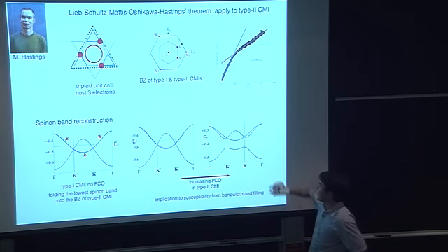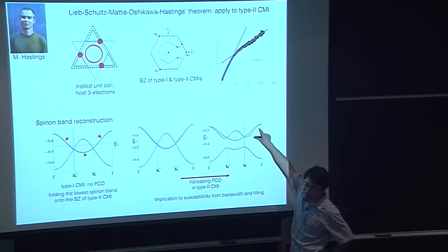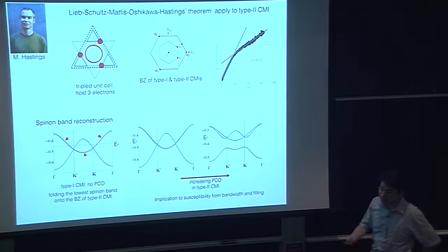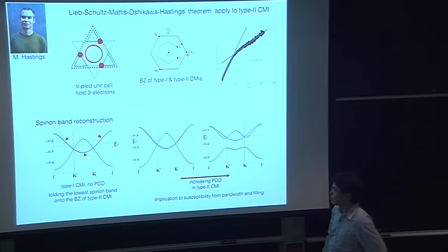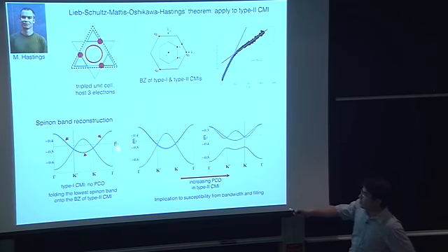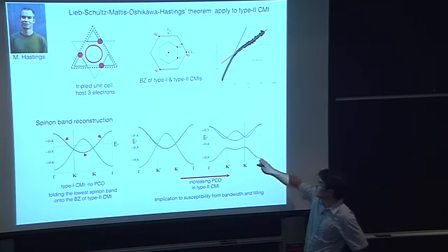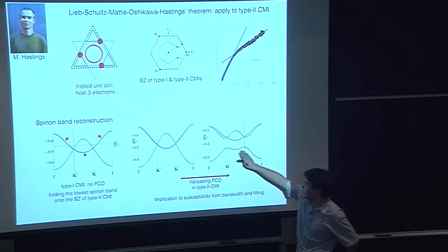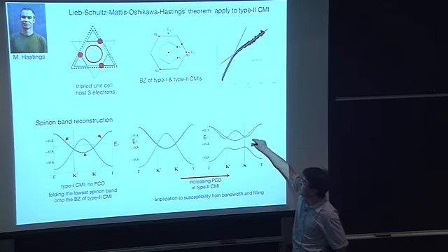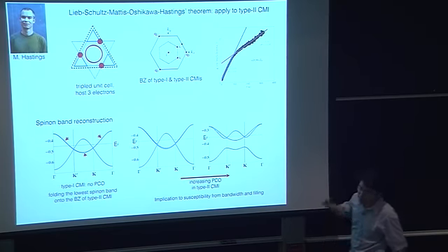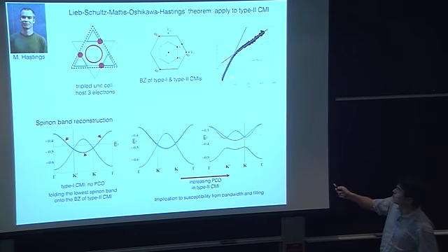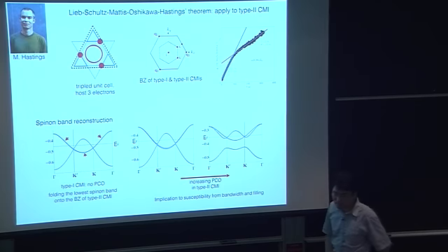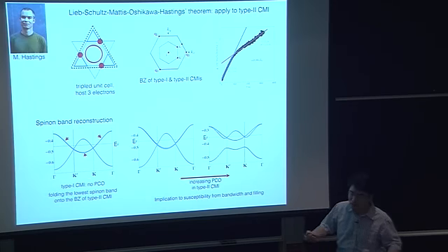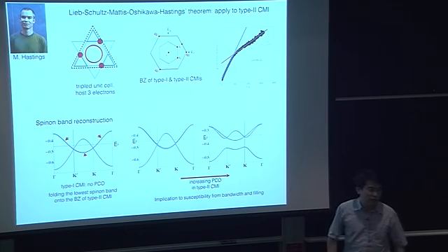On the other hand, the bandwidth of this partially filled band gives you an estimate of the Curie-Weiss temperature at low temperature. Without the plaquette charge order, the bandwidth is large. This would be the effective bandwidth. Now, if we increase the plaquette charge order, this band is completely filled and inactive to the magnetic field. Only these bands are active. The effective bandwidth measures the Curie-Weiss temperature. So this tells us why the Curie-Weiss temperature is very small at low temperature. This is the understanding from spinon band structure reconstruction when the plaquette charge order is present.